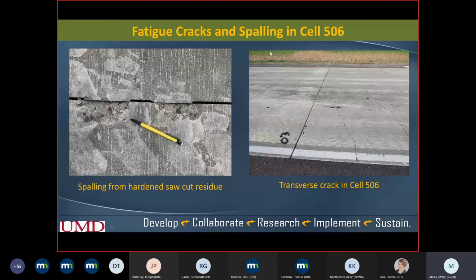All right, now let's see what distresses occurred in these 4 cells, 506 through 806. This slide is showing the spalling that occurred in cell 506. Initially, we were thinking that spalling was related to the concrete mixtures, but on closer investigation, we found out a surprising thing. Here you can see the residue from the saw cut. It actually became hard here, and that actually created some spalling.